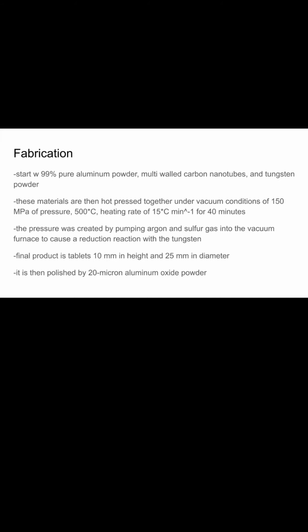The pressure was created by pumping argon and sulfur gas into the vacuum furnace to cause a reduction reaction with the tungsten. The final product is tablets 10 millimeters in height and 25 millimeters in diameter. It is then polished by a 20 micron aluminum oxide powder.